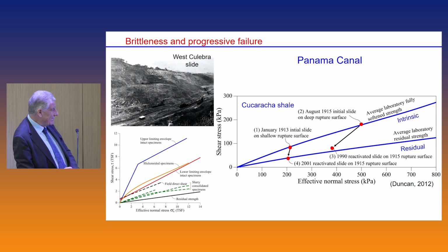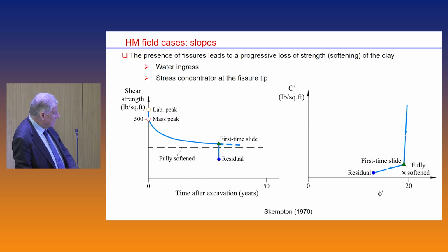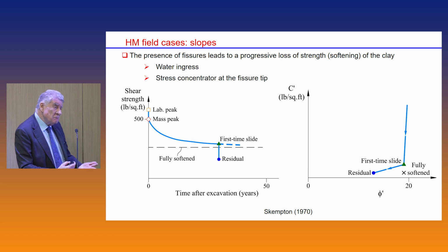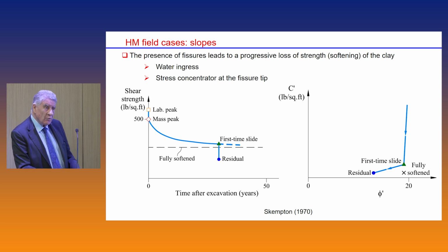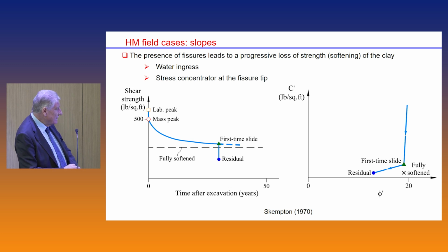Well, if we go briefly back to the Panama Canal, the same picture actually arises. These are the values of first time slides in the Culebra site, very close to the reconstituted material. When they were reactivated in 1990, 2001, what they were showing obviously was residual strength. Initially that gave rise to some theories which later on were proved wrong. The initial theory, actually supported by very illustrious people, was that there was a progressive loss of strength which was affecting mainly the cohesion due to water infiltration, softening of the material. That's how the term fully softened appeared. They reached something called a fully softened strength, and then, obviously, after failure, it went to residual, and during this stage the friction angle was reduced.